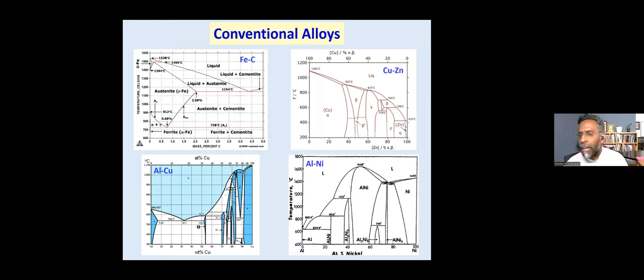So we want metals and alloys to have a reasonable ductility. The same is true with an aluminum copper alloy. There is no aluminum copper alloy known to anybody with more than 6% of copper. The moment you go to 10% copper, the alloy becomes so brittle. So these are the problems of conventional alloys.